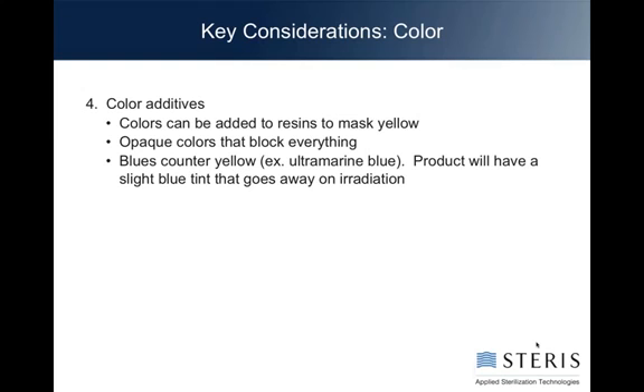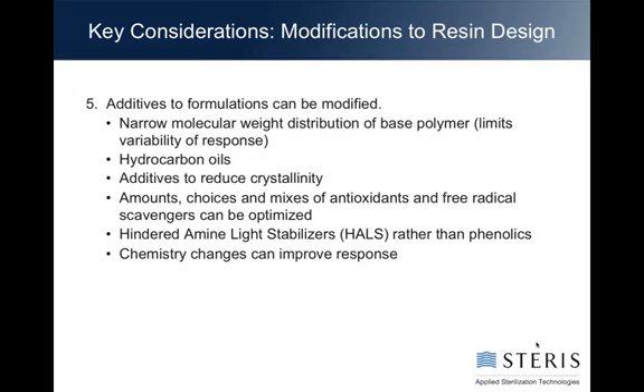The other key solution that is frequently used is the addition of blues to the actual resin. So when you have that clear-ish resin where you want to be able to see through it, frequently blues will counteract the impact of yellow. And that's because of the wavelengths of light. They will cancel each other out. What looks yellow with the addition of blue, once it's processed, will probably look clear. When you make the product, it will have a slight blue tint. But when it's irradiated, the blue goes away as well as the yellow. So it's actually a very nifty thing to see. Okay.